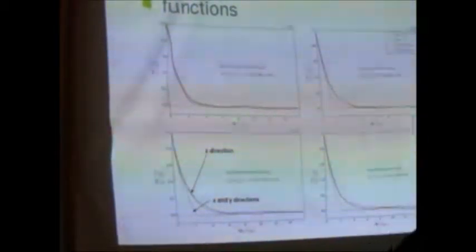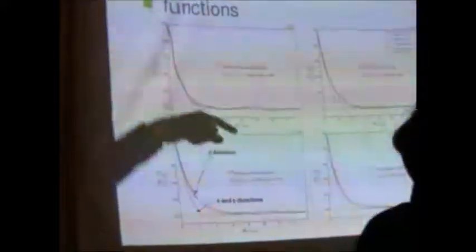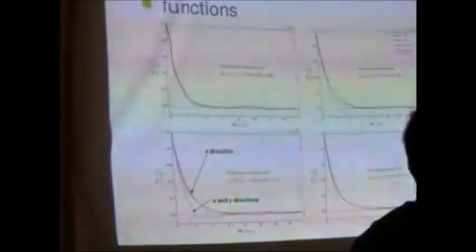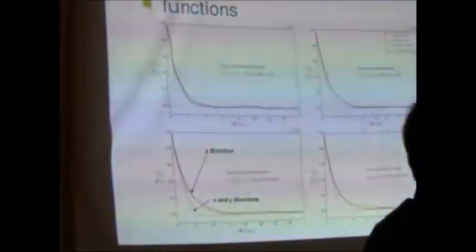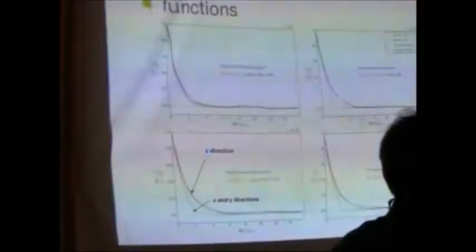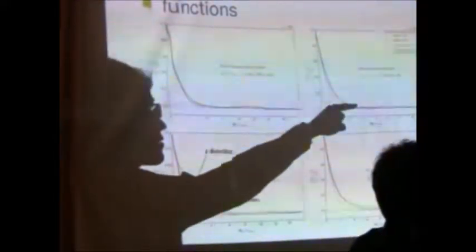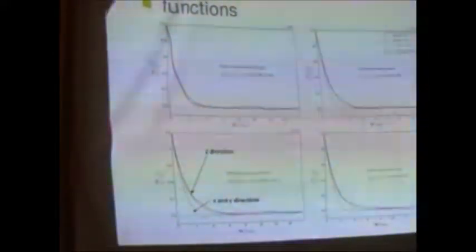At first, all 3 autocorrelation functions are merged in a single curve, and you can evaluate the length scale parameters. As soon as you start applying a deviatoric stress, the autocorrelation in the horizontal direction, which is the dashed black line, decreases faster than the one in the z direction, which is the direction of the deviatoric stress and also the direction of the growth of the force chains.